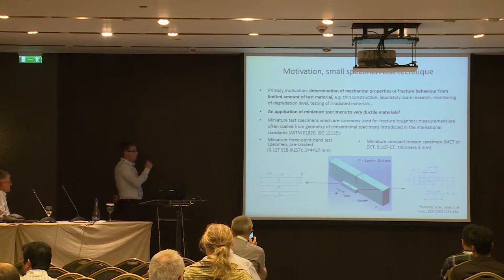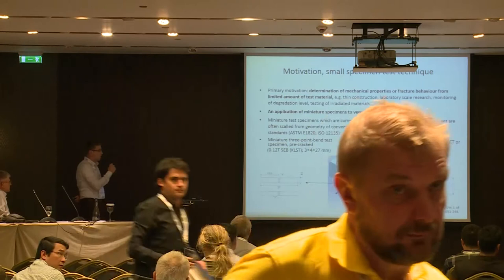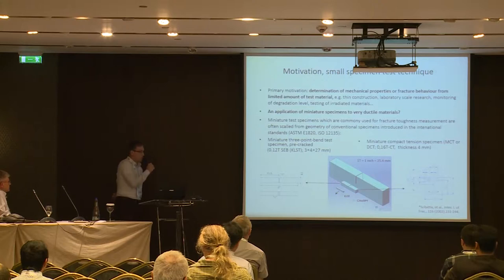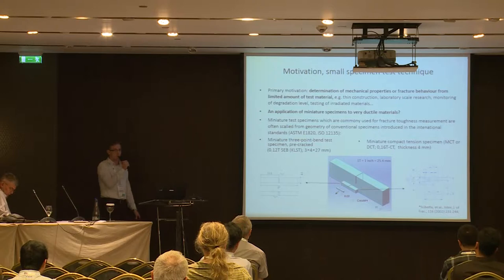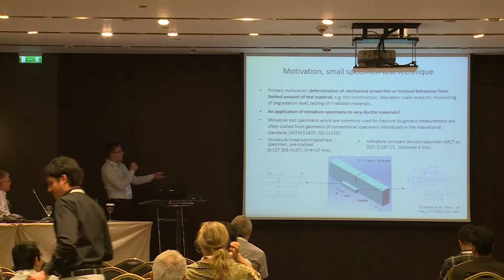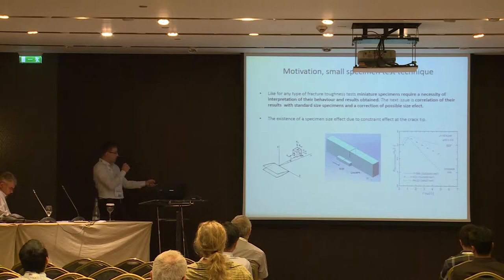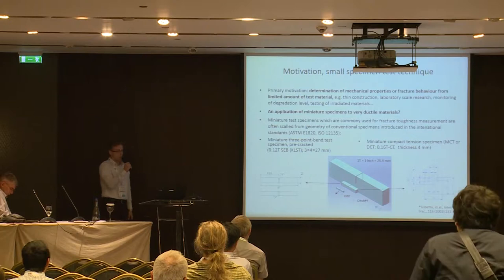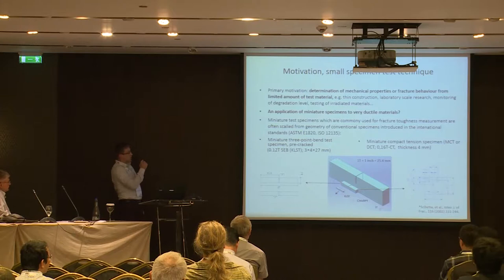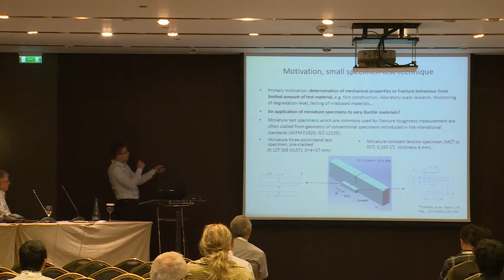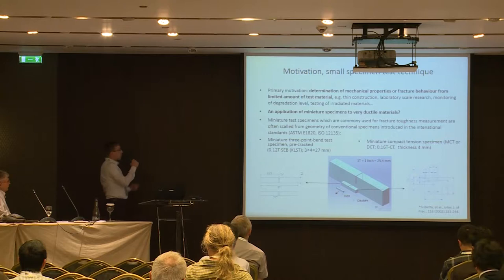What is the motivation for using small specimen sizes, which can conflict with quite demanding fracture toughness standards and measurements? The motivation is straightforward: either you don't have enough test material — which can naturally occur in thin constructions — or in laboratory-scale research, fracture toughness testing is very demanding in terms of test material. When developing new alloys, we usually have a limited amount of material. With small specimen sizes, you can also more easily monitor the degradation level of components.